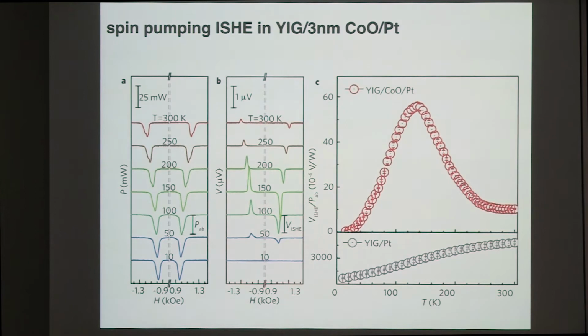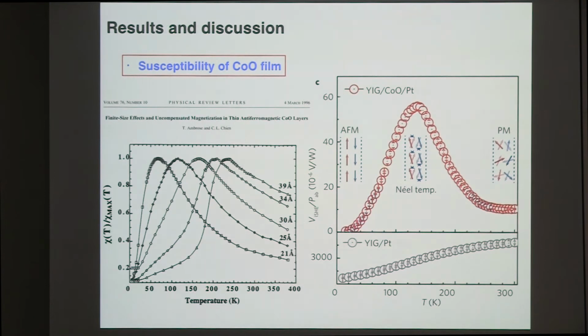So the problem for us then is to explain why there is a peak here. If you look at the literature on the susceptibility of cobalt oxide, like by the Charlie Chen group, more than 20 years ago, they showed that for cobalt oxide thin film, if you change the thickness, you can see this kind of peak position around the Néel temperature, and it will increase with the cobalt oxide thickness. So at the time, we naively thought that this point should be the Néel point. But the first check, very easy, is that we can check the thickness dependence.